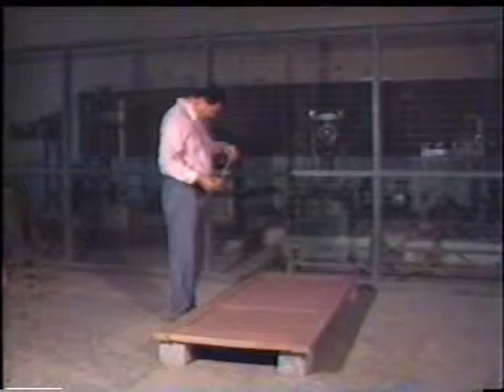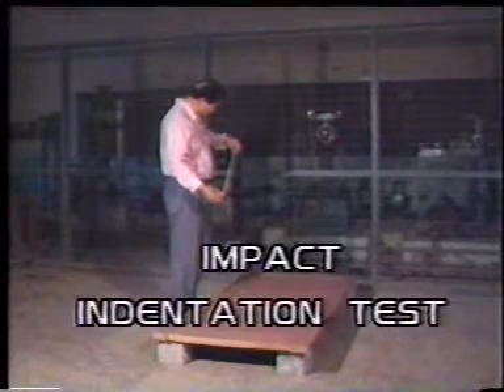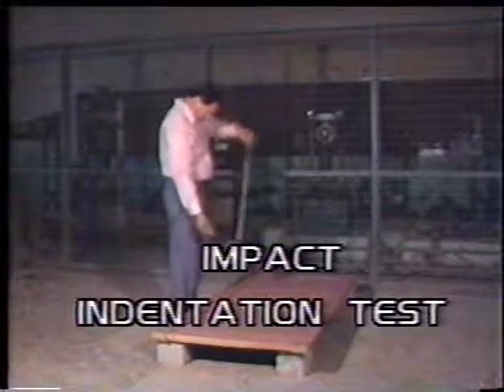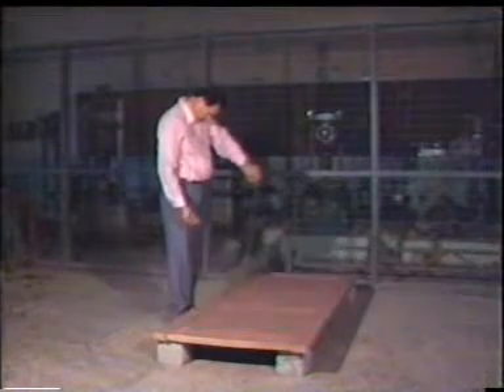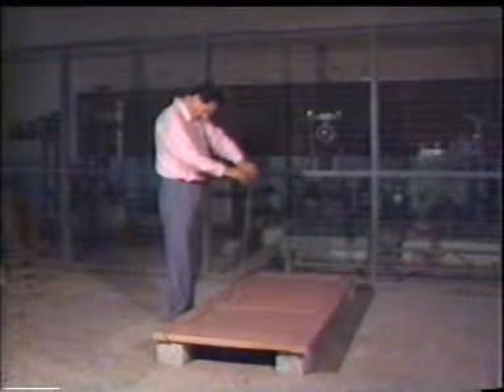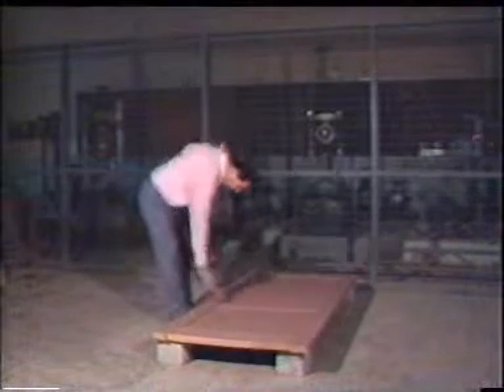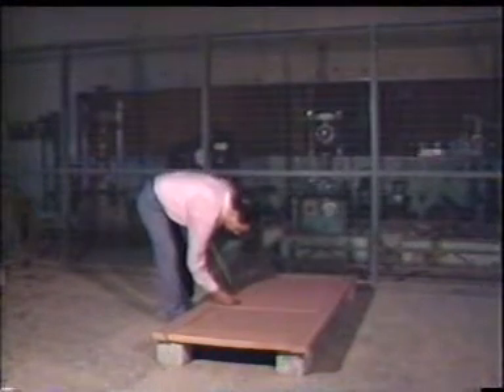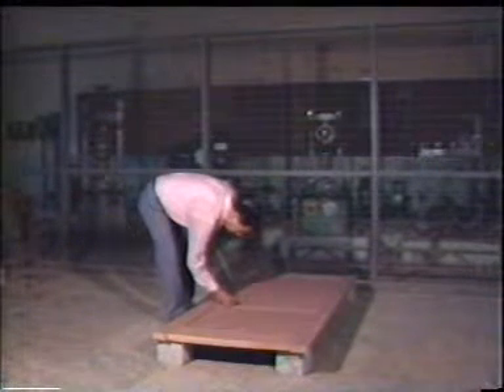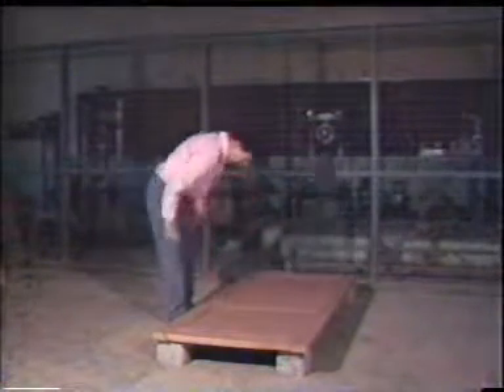The third laboratory test is the impact indentation test. The shutter is placed on four supports at the corners. A steel ball weighing 450 grams is dropped from a height of 75 centimeters at 10 randomly selected points away from the edges on any of the inserts, stiles, or rails.